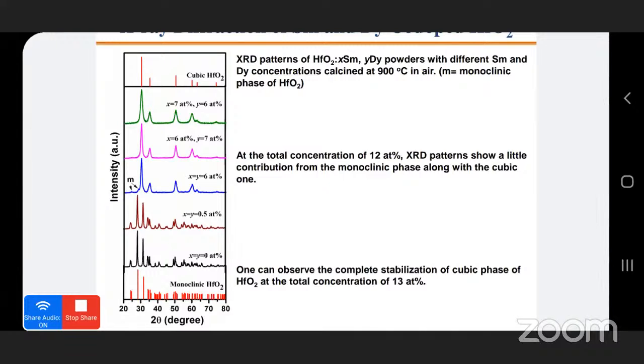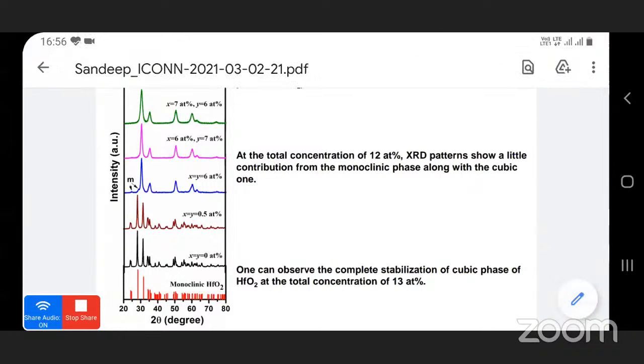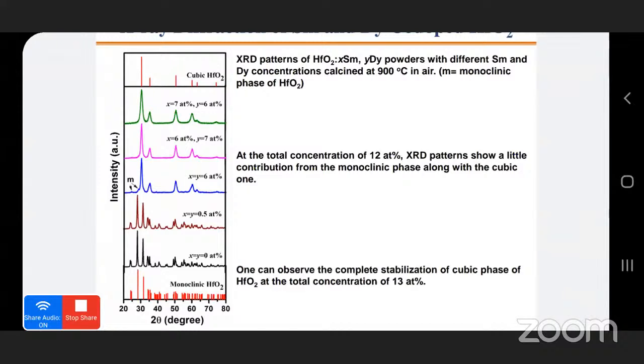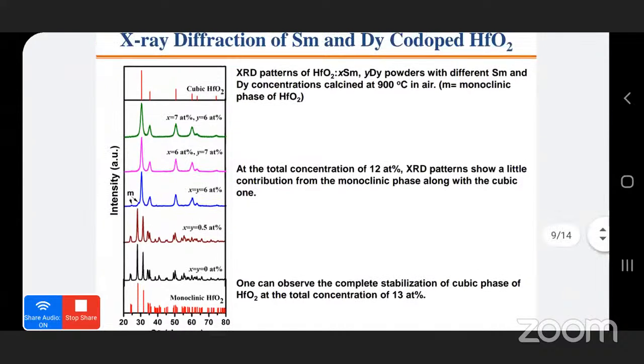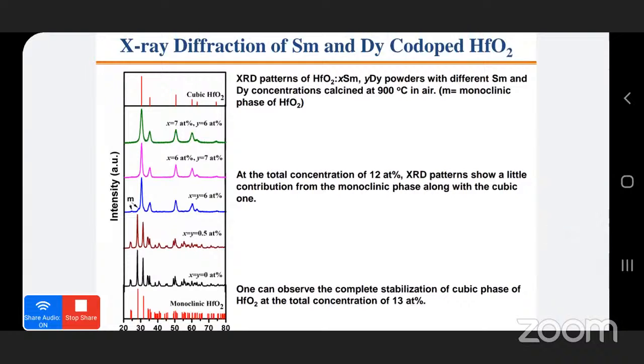But as we increase the total concentration of this system to 13 atomic percent, whether dysprosium or samarium has 6 or 7 atomic percent, giving a total concentration of 13, okay, I'll just summarize it very quickly. For 13 atomic percent in the Dy and samarium co-doped system, we can stabilize the cubic phase at room temperature.